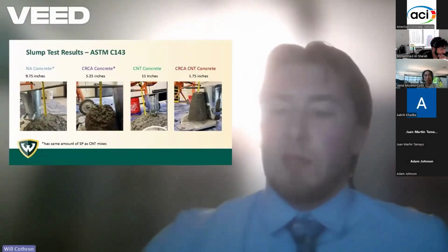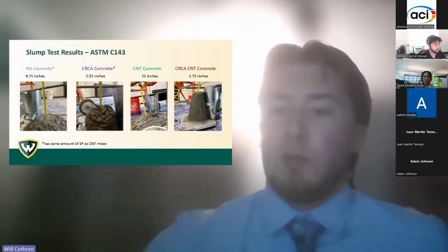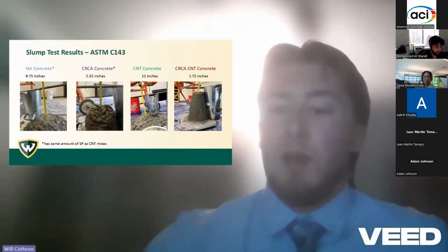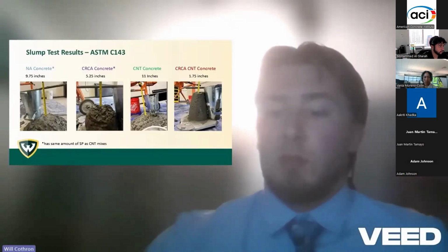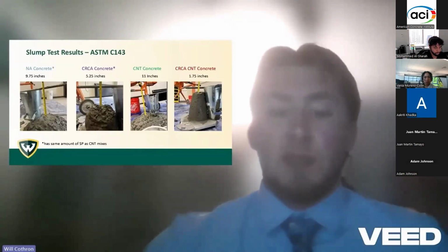With the introduction of CNTs, the slump increased to 11 inches, indicating improved workability and flowability. CNT dispersion likely contributed to lubricating effects, enhancing workability. Interestingly, the CRCA concrete containing CNTs exhibited a significantly reduced slump at 1.75 inches, likely due to a combined effect of denser aggregate surface due to carbonation and the presence of CNTs.